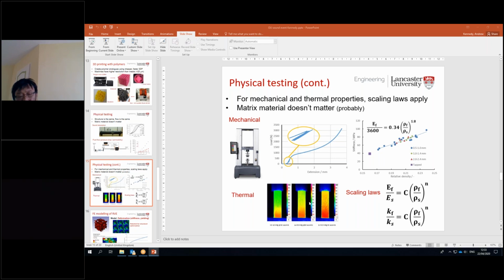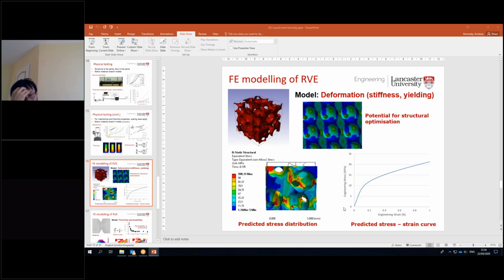But in fact, for both of these types of properties, the scaling laws that are shown at the bottom apply very well. So that means we have a sort of normalized value for like the modulus or the thermal conductivity based on the ratio of the behavior for the foam compared to the behavior of the solid material. And these then relate to the relative density of the material, the ratio of the densities, and the constants relate to really the architecture of the structure. So it means that actually we can study the performance based on the architecture alone, and it can be system independent.